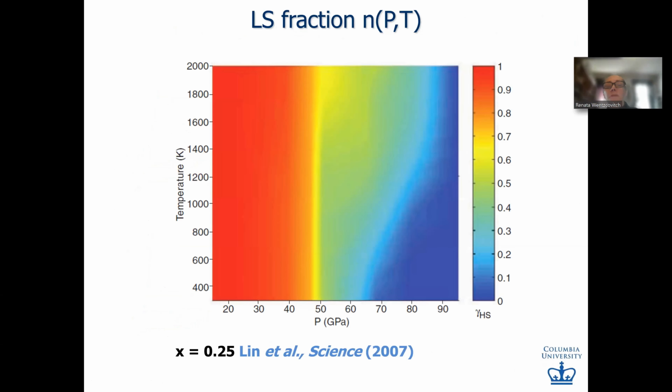Okay, so this is the experimental measurement in 25% iron that came out in 2007. The difference is that here the slope is not constant, but it starts with a vertical slope and then broadens, and then the slope becomes vertical again above 1500 Kelvin, let's say.